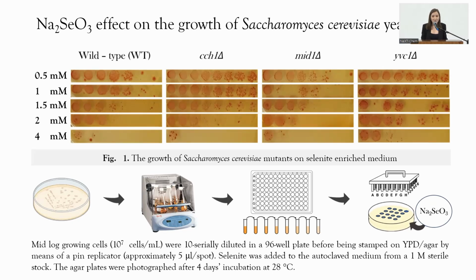The second observation would be that the growth of these strains was severely inhibited in concentrations exceeding 2 millimolar sodium selenite. But even more interestingly, the MID1 knockout strain was the most affected by the exposure to sodium selenite, which means that yeast cells might need the MID1 calcium channel to survive the sodium selenite-induced stress. The YVC1 knockout strain was the most resistant one.